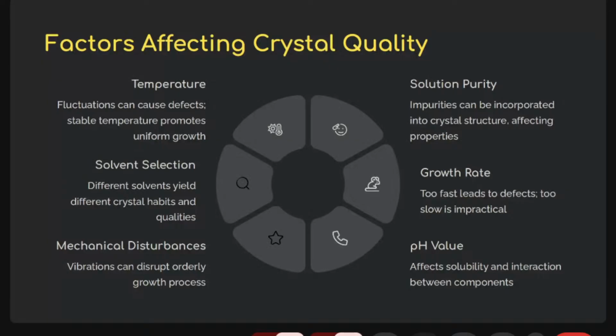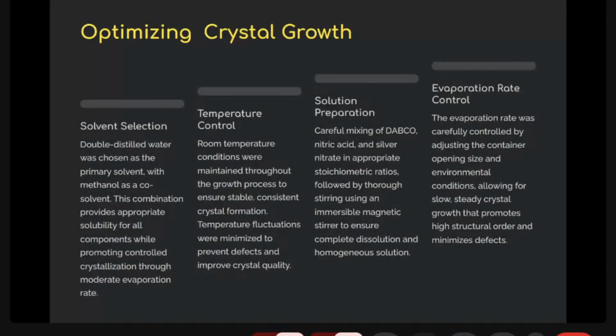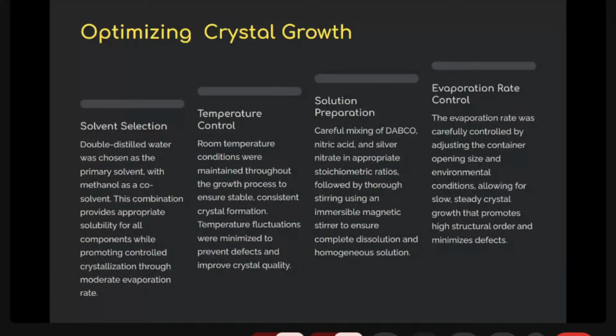Now, crystal growth is also a time sensitive process. Grow too fast and molecules do not get sufficient time to arrange into the lowest energy or most stable configuration. This results in vacancies or irregularities in the crystals. Now, growing too slow, the process becomes impractical for scaling or research. The ideal scenario is to find the balance where the growth is slow enough to maintain the structural integrity but fast enough for practical production. Now, optimizing a crystal growth, we need good solvent selection, temperature control, then the solution preparation, and the evaporation rate control. So these are the four factors we need for getting a good quality